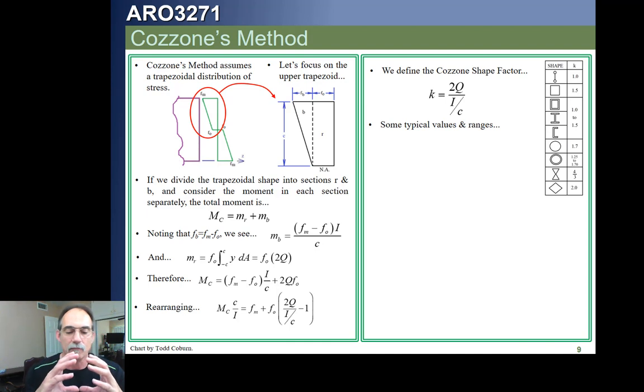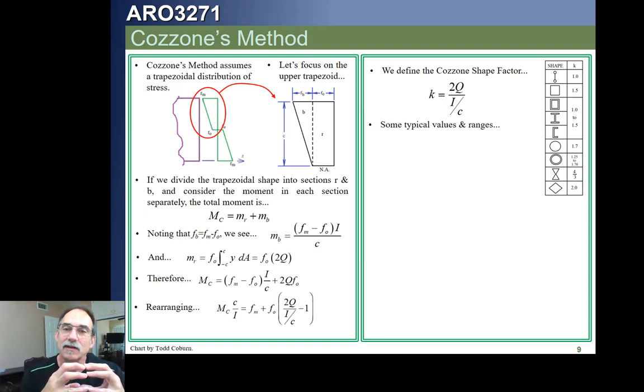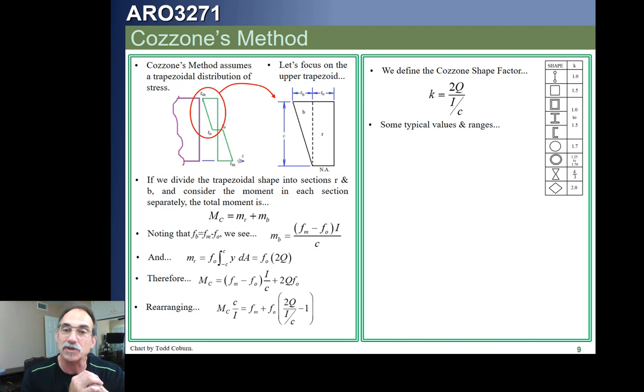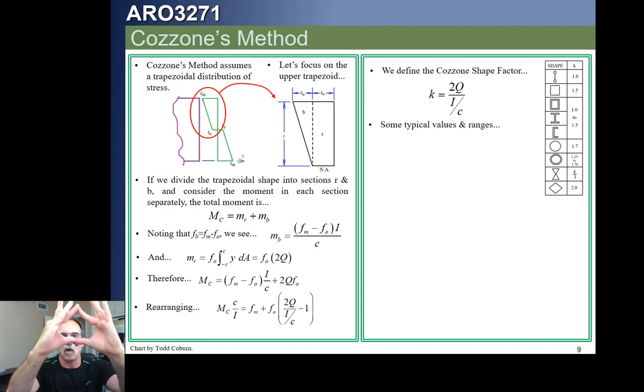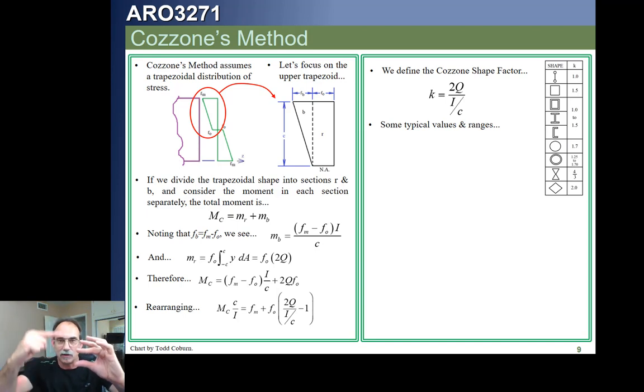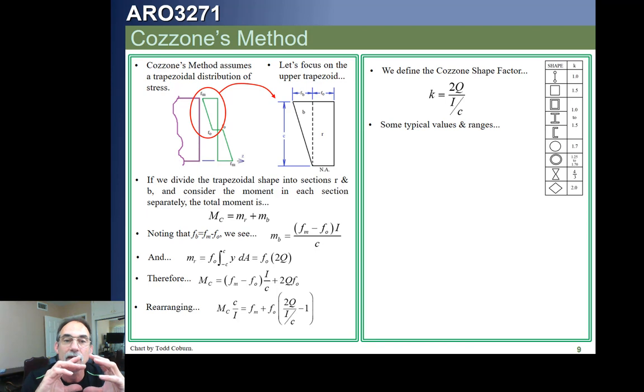The more area we have near the neutral axis, the more benefit we'll get from doing plastic bending analysis. The less area near the neutral axis, the less plastic bending analysis will help. A lumped section is already very efficient for carrying bending because all the area is pushed as far away from the centroid as possible — therefore it gets no benefit from a plastic bending analysis. But if we have a reverse hourglass section where all the area is at the neutral axis, when your material reaches Ftu top and bottom, it's only a tiny fraction of the total capability.